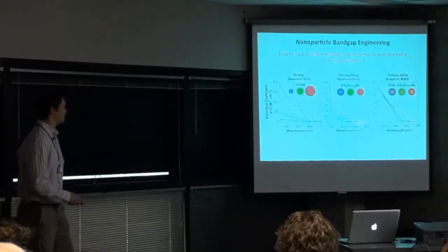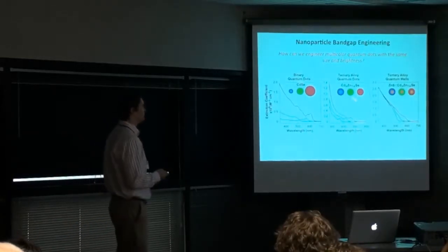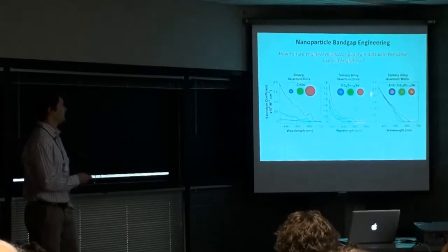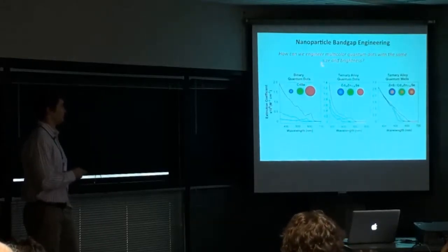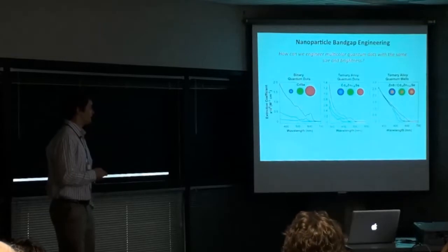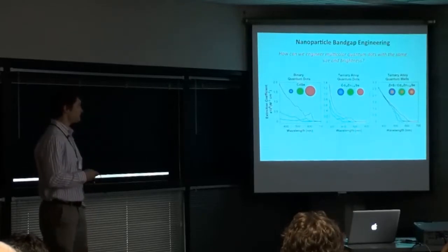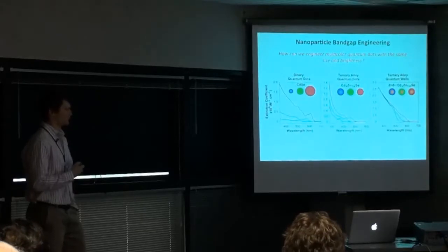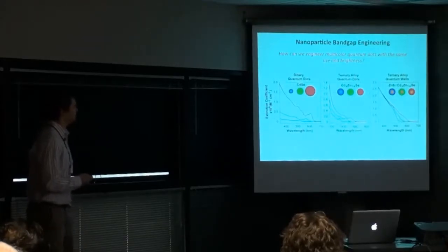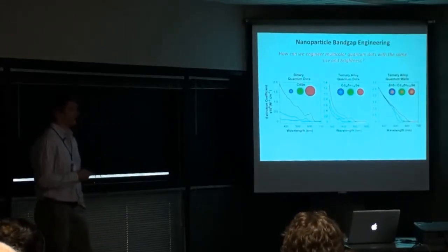We want to get around this by engineering particles away from size-based normalization. An alternative is to use alloyed materials — taking a binary cadmium selenide material and alloying it with a secondary material to form a ternary alloy, in this case cadmium zinc selenide. This allows all sizes to remain the same while changing fluorescence emission based on material composition alone. This reduces brightness differences from the typical 15 to 20-fold range down to two to three-fold differences.